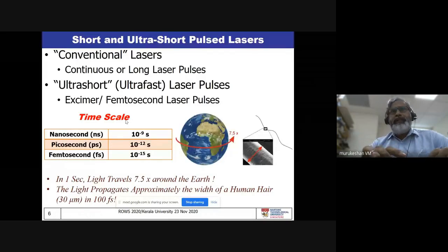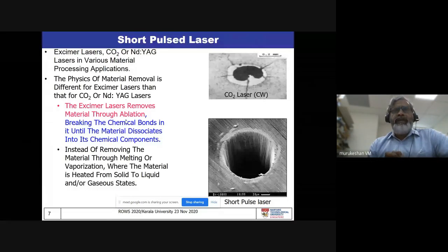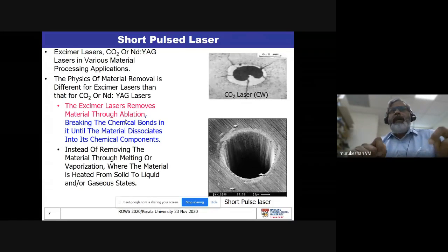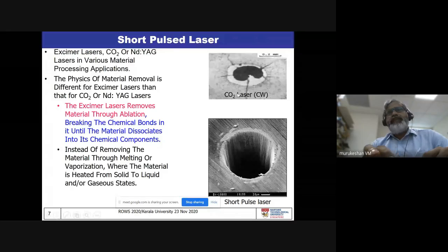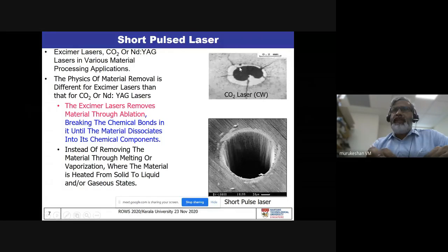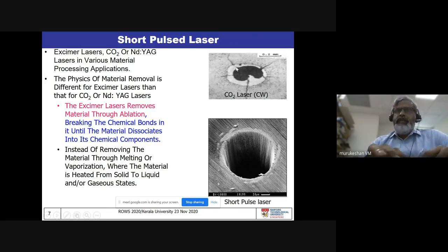Basically, what I would like to highlight here is how the material processing occurs when you are using, for example, a carbon dioxide laser or a neodymium YAG laser in the continuous mode or long pulse mode, as against short pulse lasers such as excimer lasers as well as femtosecond lasers. And you can see that when you use a continuous wave laser such as carbon dioxide or neodymium YAG lasers, there are always certain side effects such as the heat affected zone, which also forms this kind of recast. We normally call this HAZ, and this is the origin of very many crack propagations. So we need to be very careful that we are really working at the threshold optimum region. Otherwise, you are really going to make this problem much more significant and detrimental.